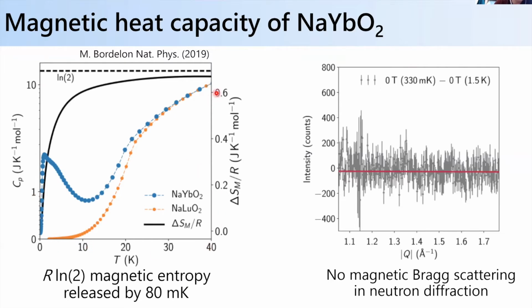And we can remove the structural component, or the lattice or phonon contribution to the heat capacity, and isolate the magnetic heat capacity by measuring a non-magnetic analog material, sodium lutetium O2, which forms in the same structure. Then we can subtract the two and integrate the magnetic entropy, and it indeed approaches R log 2, which you would expect for a J effective 1/2 system, okay?